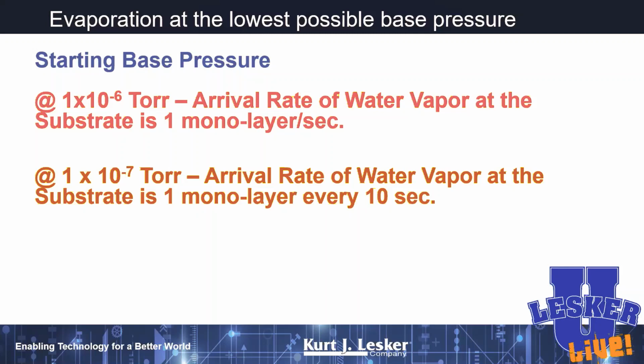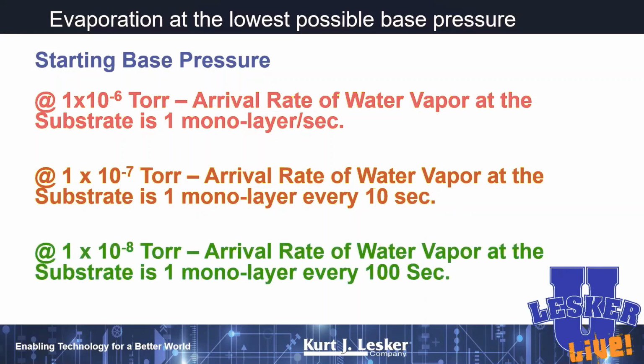So if you're trying to get something to stick on your substrate and it's got 10 layers of water on top of it, you're going to have a tough go of it. If we go down another decade, we get another 10 seconds. If we go down another decade, we're up to sort of a minute and a half or so before you develop that monolayer of water. So generally speaking, even in sputtering, the lower in base pressure you can go before you go up to your operating pressure, the better the films are going to be, with fewer inclusions of other strange gases.